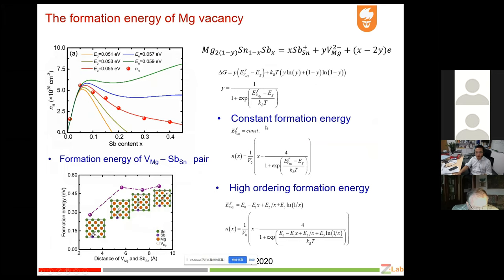However, if we consider a constant formation energy for this vacancy, we cannot use this kind of formula to fit this experimental result. We need to add some extra term, like this kind of formula. It should have a term related to the antimony content, and then finally we can obtain a good fitting. That means the formation energy of the magnesium vacancy is related to the content of antimony.